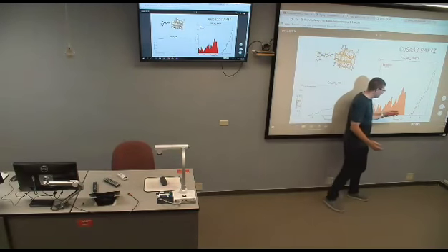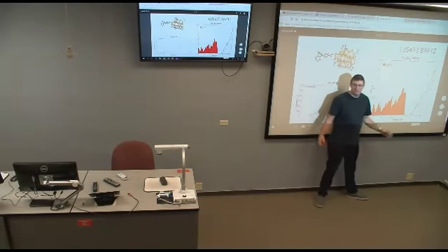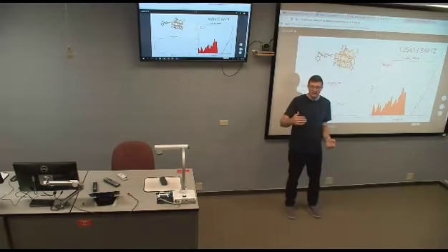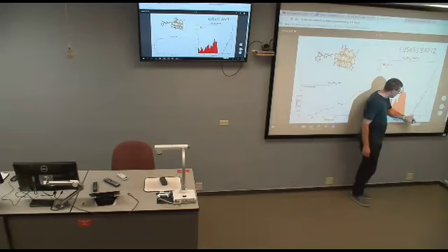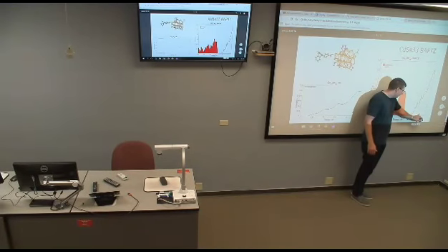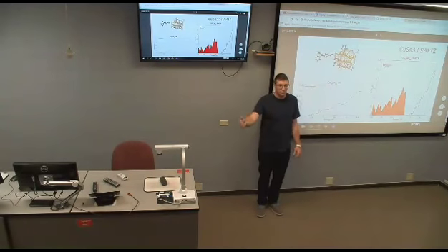But the other thing I want to talk about is, this gap here aligns very well with what they measured experimentally for the work function for these extra states coming in from the organic ligands. The only issue is what they found with their band gaps was the valence band that was going to be almost another 1.2, 1.3 electron volts above that.